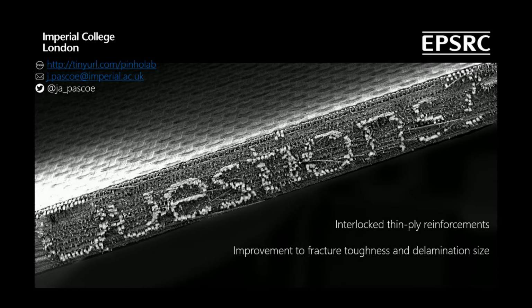To conclude, in these videos we have presented our research into the creation of interlocked thin-ply reinforcements, which can be used to reinforce selected interfaces of a regular composite layup. These reinforcement units were able to improve mode 1 fracture toughness as well as post-impact delamination area.